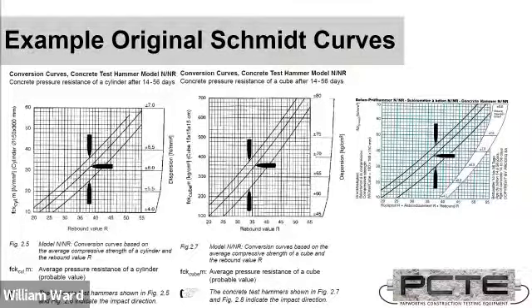So I've got 3 different conversion curves for an original Schmidt hammer here. The one on the left is a cylinder curve for 150 by 300 millimeter cylinders. So the same ratio we use in Australia. The middle conversion curve is a conversion curve made using 150 millimeter cubes. So that second conversion curve, even if you put the exact concrete mix into those cubes and broke them, your MPa values would be higher when breaking cubes than if you broke cylinders. You need, if you want to use a curve created using cube samples, to correct back to a cylinder sample curve.